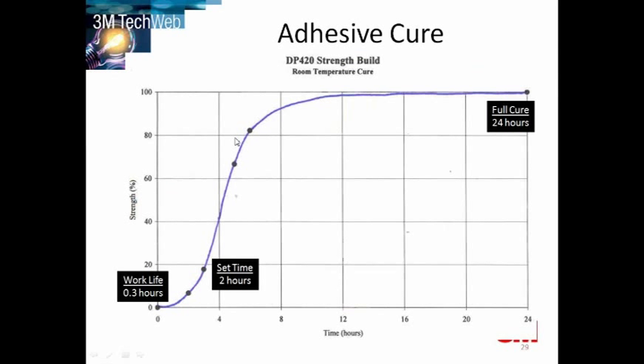An adhesive cure. This is very important — understand the work life of the adhesive, the amount of time needed to mix and apply the adhesive and get the parts fixed together. For certain applications, for example large panel bonding, you will need a long work life because you physically need a lot of time to apply the adhesive to large panels. Set time is the fixture time — the time to handling strength.